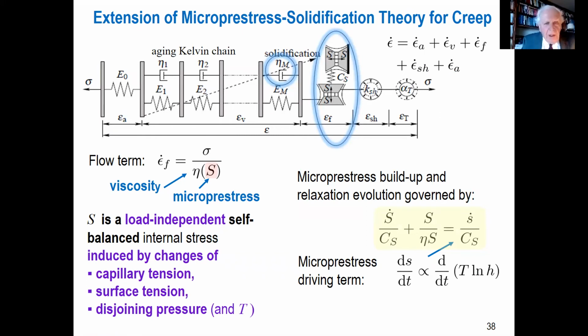Now then, of course, we must model creep. That has been studied for 50 years. Now there are two basic models. One is solidification. The essence of solidification theory is that thermodynamically it's impossible to model it as a time-dependent material. One must assume thermodynamics can be modeled for a material of constant properties, which means there are constituents which are non-aging. For example, CSH as such on a nanoscale is non-aging, and their volume is growing, or they are getting interlinked by polymerization, and that works thermodynamically properly.